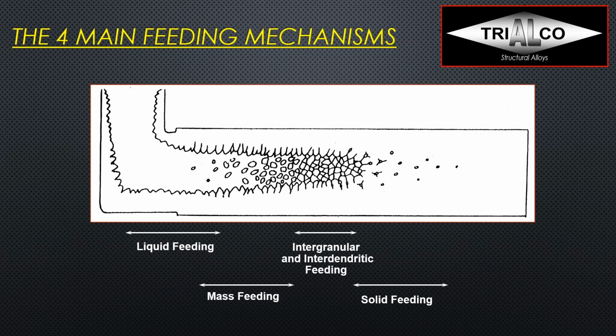So now that we covered fluidity, we have 4 different feeding mechanisms. The first one is quite obvious. As long as I pour the metal in, I have liquid feeding and I'm filling out the mold. And then when it slowly solidifies, usually away from the walls, I have mass feeding. And then I have the grains forming out, and then it's called intergranular or interdendritic feeding. And then after that, I get into solid feeding, and that's an important part in high pressure die casting or squeeze casting, of course.